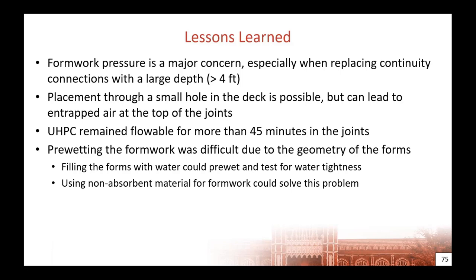While it was great and a lot less invasive than a typical repair, one of the issues that we found was that we would top off a joint and then walk away and move on to the next joint. When we went back and looked at it again, we'd see that the material had settled. Because it is such a viscous material, it tends to trap air bubbles, but those air bubbles will eventually work their way up to the top. So when you initially top the material off, it's still got entrapped air that's going to work its way out. So that's something to consider: you may have to top it off incrementally as you continue your pour until all of the air is removed.